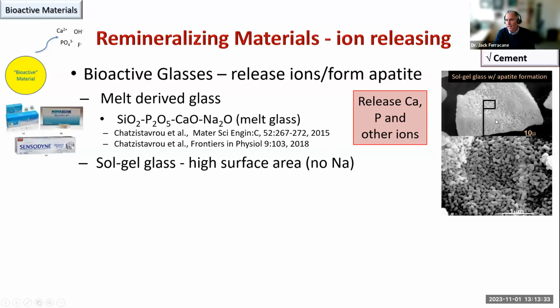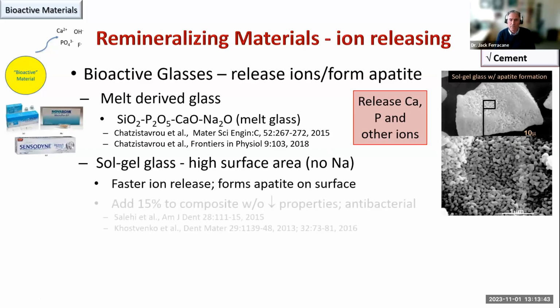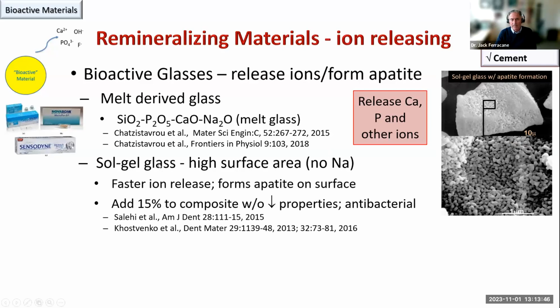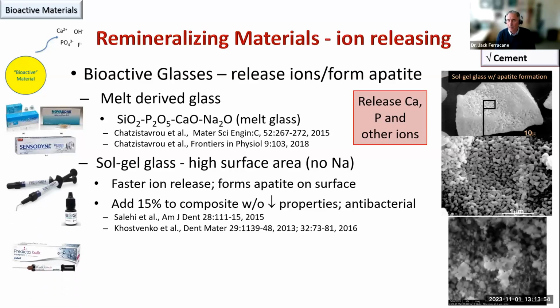And we can see this is the glass, and then this is calcium phosphate mineral forming on the surface of the glass, which again becomes apatite in time. So these sol-gel process glasses had very fast ion release, and we added them to dental composites at about 15 weight percent. And we showed that we could do this without a degradation in the properties of the material, and they had an antibacterial effect.